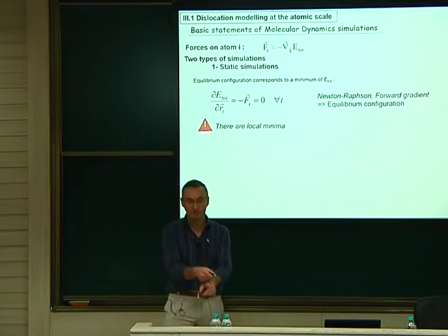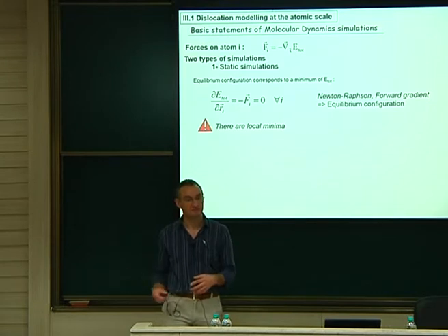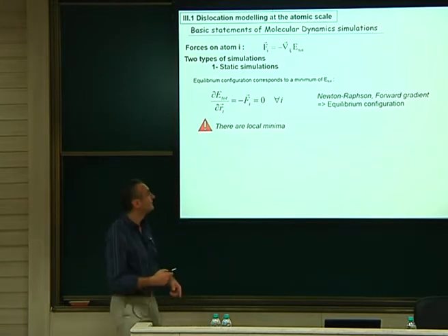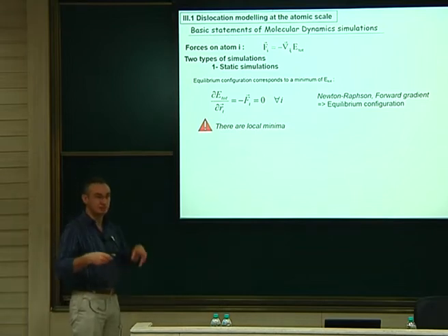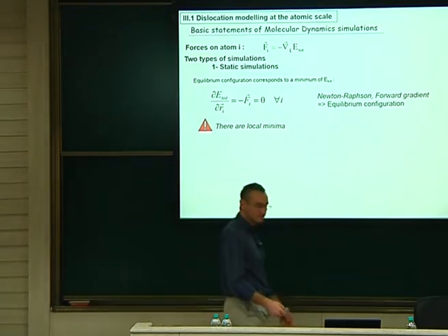Okay? Don't put your dislocation and start your simulation straight after, because you will have some artifact. The beginning will just be this relaxation stage. It's not what you are looking for. So this is always starting like that. First, you need to have a static simulation to be sure that you have something which is physically correct.